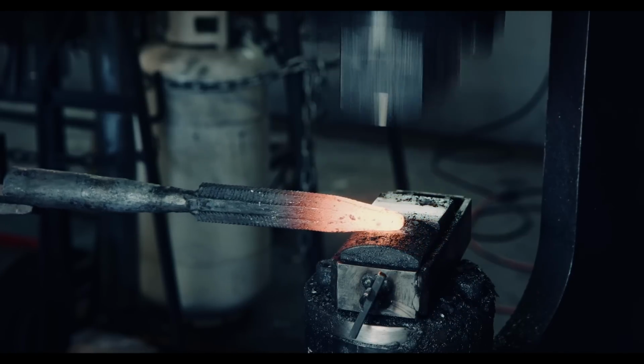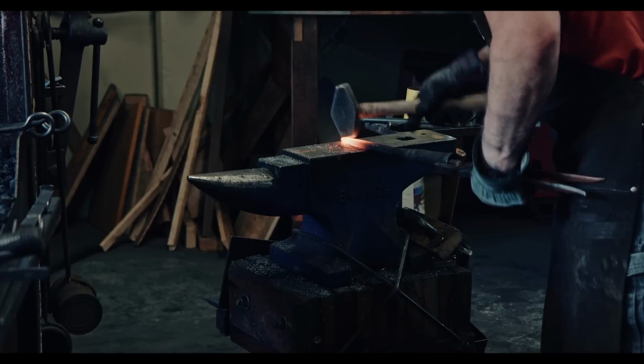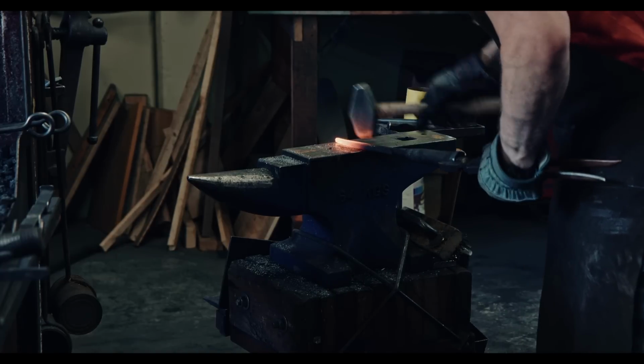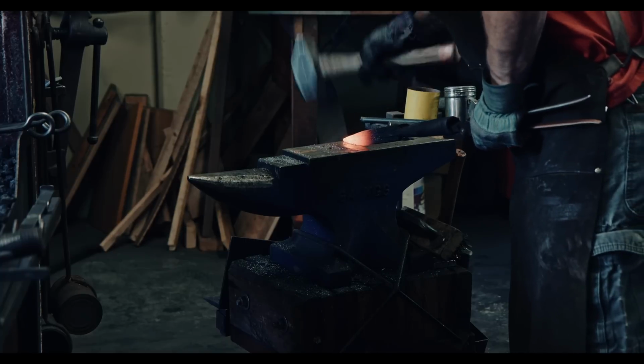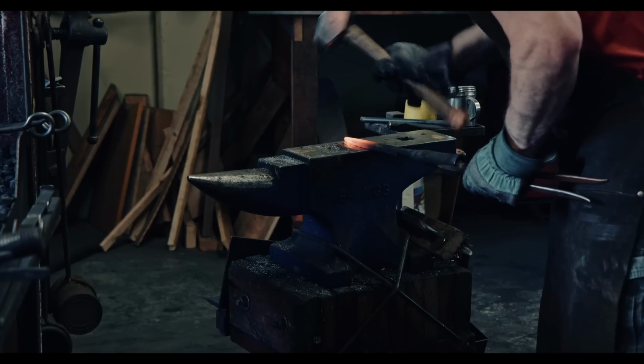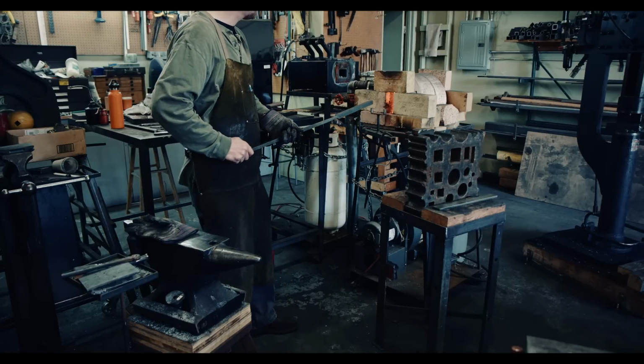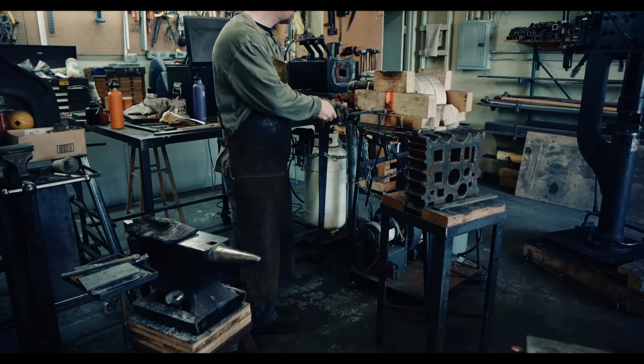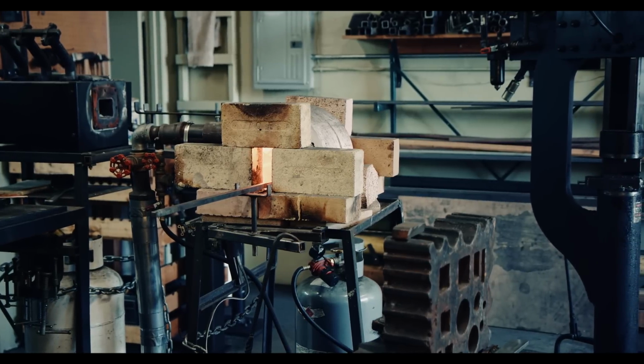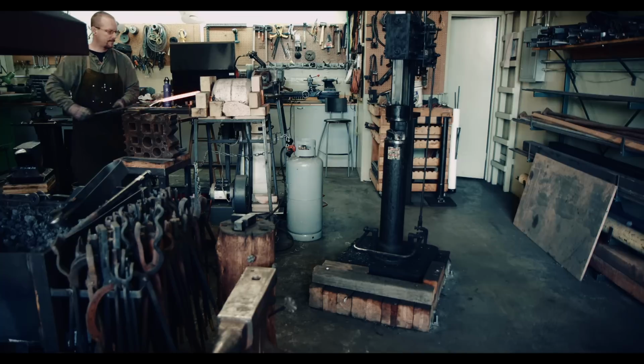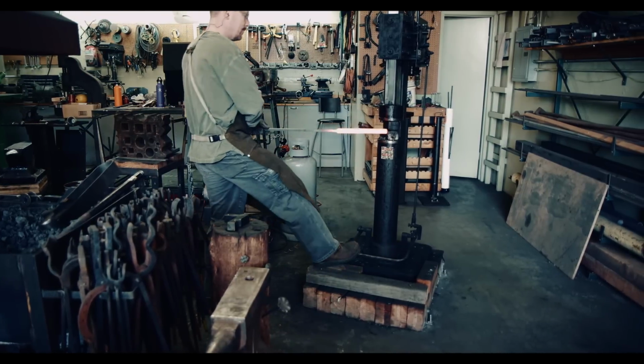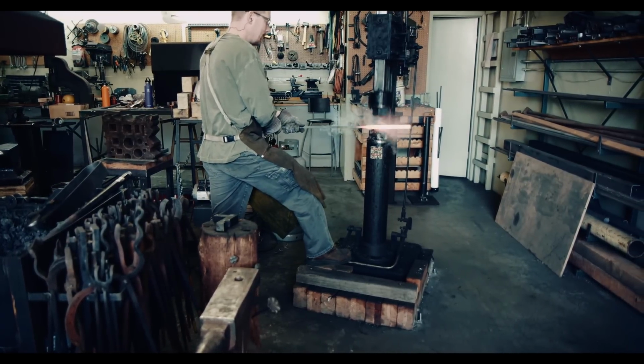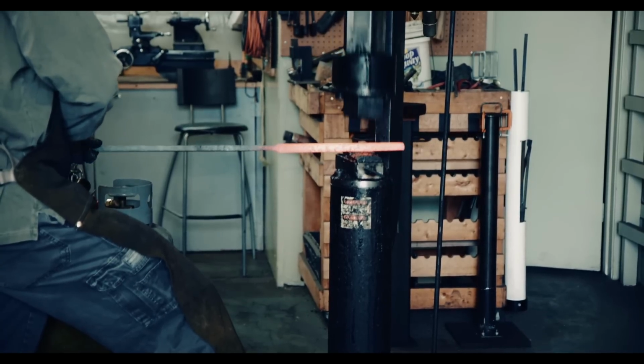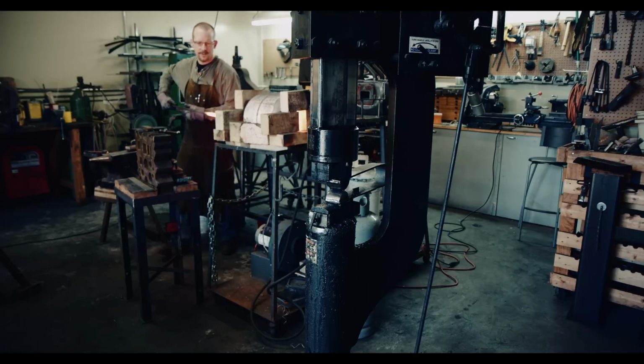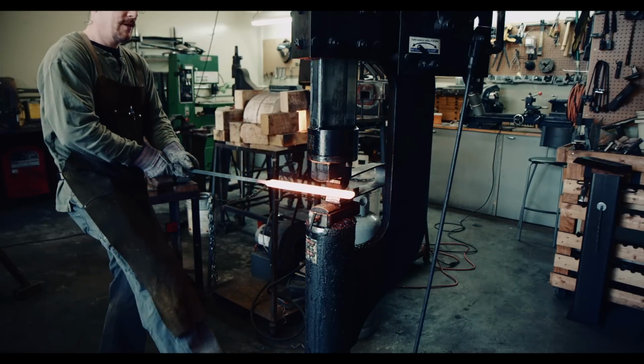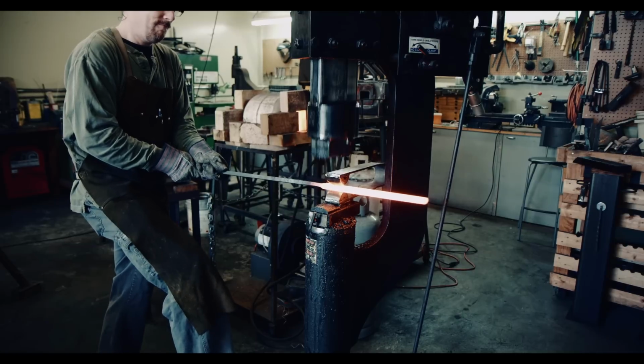In preparation for the next step, I need to taper the tip into a much sharper end. This is necessary since we need to fit the cutting edge of the spear over the core that we have built up so far. Now it's time to prepare for creating the wolf tooth pattern. I already have a block of reasonably high layer steel we will be using for the cutting edge. Before it can be used, I need to forge it to the right dimensions. It needs to be about 3/8 of an inch thick and much wider. I want the bar to be at least 2 inches wide, so that the spear core will fit right into the center of this bar.